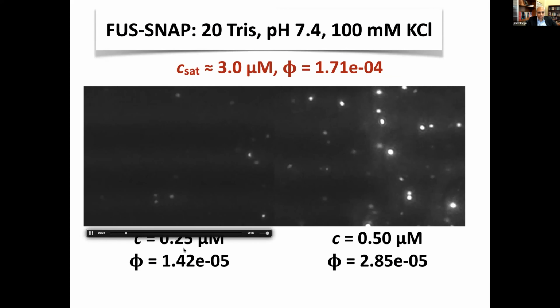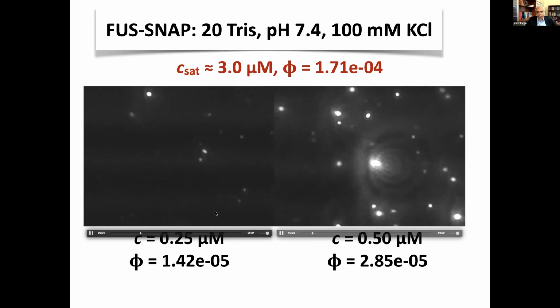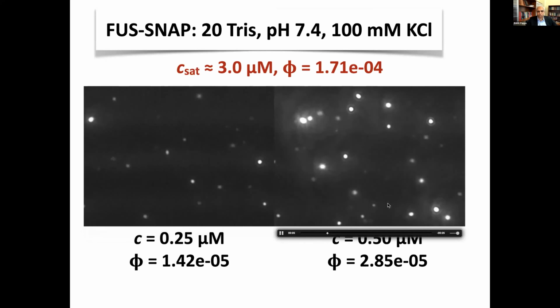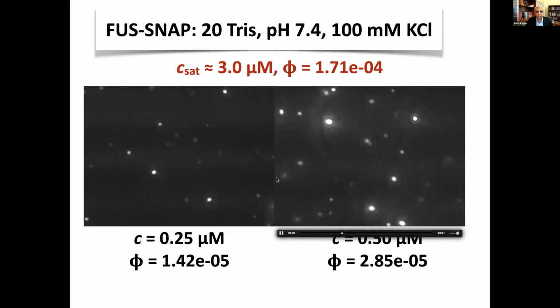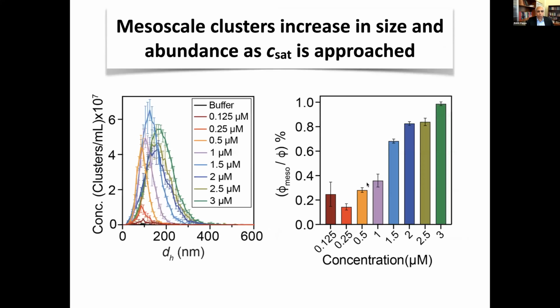So here in deeply subsaturated solutions, you see these clusters, and notice that the abundance increases as we increase the concentration by a factor of 2. These are all below CSAT. You see these clusters running around. One can quantify the abundance at a series of different concentrations. Notice that in accord with the theory, these distribution sizes shift to the right, meaning they take on higher sizes. From these data, we can calculate the relative abundance of mesoscale clusters, right? And these large species that are scattering detectable make up about less than 1% to 1% of the solution. You might sneeze at that, but from a nucleation standpoint, it's completely right.